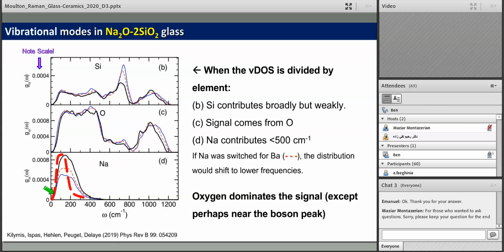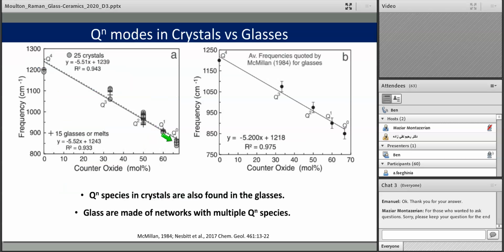The important aspect is that in all cases, oxygen is the thing that Raman spectroscopy probes strongly. And so it is changes in oxygen almost ubiquitously that are the strong changes in the spectra that you will observe upon measuring it. I mentioned that these stretching modes are quite consistent.